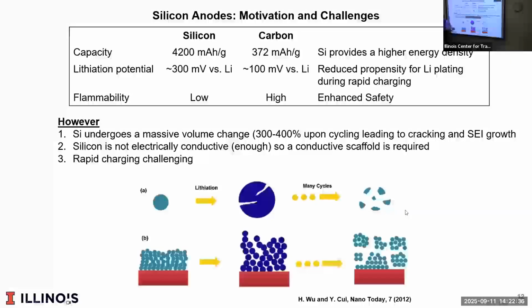Okay, so here's the silicon. Silicon has 10 times the energy of carbon. If you take the negative part of the battery and change it from carbon to silicon, you get 10 times improvement in the negative terminal, which gives you 2 times or so improvement in the whole battery. The problem is, and I know people here know lots about mechanics, when you put lithium into silicon, it gets 3 to 4 times bigger. So how do you build a battery where half the battery is going like this every time you cycle it?